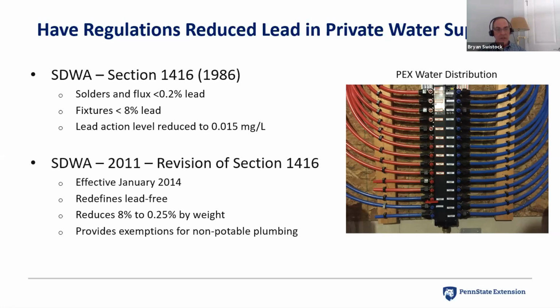There have been various tweaks to this, and there was a revision in 2011, which took effect in 2014, which started to redefine what lead-free meant, started to reduce that fixture level from 8% down to 0.25%. So it started to tweak the regulations to get better control over lead sources, even within fixtures, not just within the solders, which was a lot of what the original Section 1416 did. What we've seen over time are these regulations taking effect and reducing the amount of lead solder, reducing the lead in fixtures, so that even if you have corrosive water, we should theoretically be seeing less and less lead as older homes are renovated and they start to use different systems.